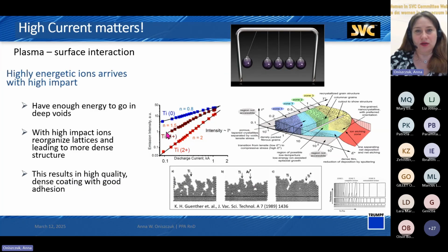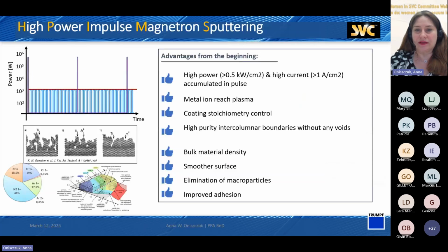And what will happen? When you have a very energetic plasma, you have a very good plasma-surface interaction. You have these accelerated ions that arrive at the substrate, and by hitting one another, they can densify the structure. So the more ionized plasma, the more plasma current you have, the better structure you get: more dense, fewer voids in between, and thus the mechanical properties of the coatings will be much better. That is very good for a lot of purposes, and you can have a very smooth surface. You don't have so many macro particles. You can also improve the adhesion, and you can get very good control over the stoichiometry of the process.